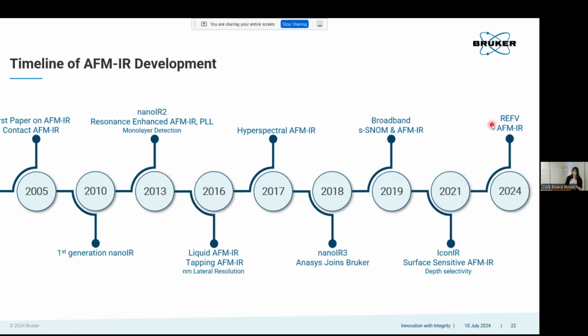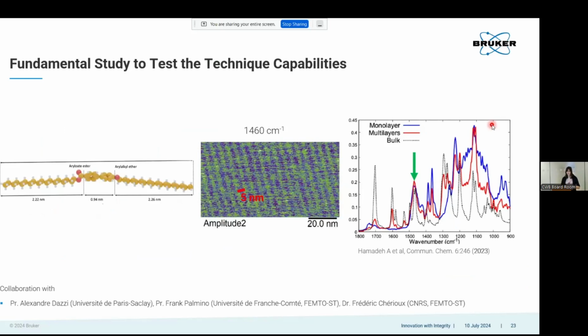We've released a few additional platforms since then, but we've really looked at how we can push the technology further and further. So one of the examples I have here is another fundamental study where we're looking at an even thinner material and even shorter length scales. So this is an example of a small molecule. You can see it's about 5 nanometers long in total. Cast them out onto a surface such that they self-assemble into a herringbone. So they kind of stack over each other. But it's still a single layer of these materials. They're just lined up side by side, like in the first class seats on an airplane.